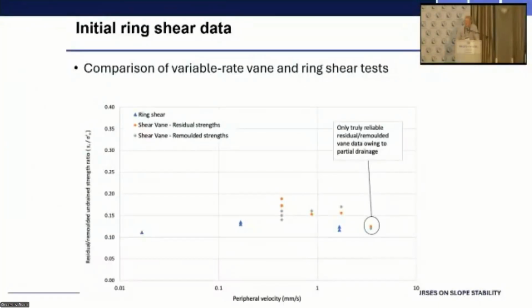So here we've got some data. This is large strain strength ratio against what we've called peripheral velocity. So it's trying to relate the velocity at the tip of the vane, or the edge of the vane faces, so converting that to a velocity, and comparing that with the constant volume ring shear. And you can see that the agreement there is really not bad when you compare it with a lot of traditional kind of plots of strength. That variation of 0.02 or so is really pretty good, but it's also indicating the effect of shearing velocity or shearing rate on the peak undrained shear strength. So you're probably getting some kind of small viscosity effects there.